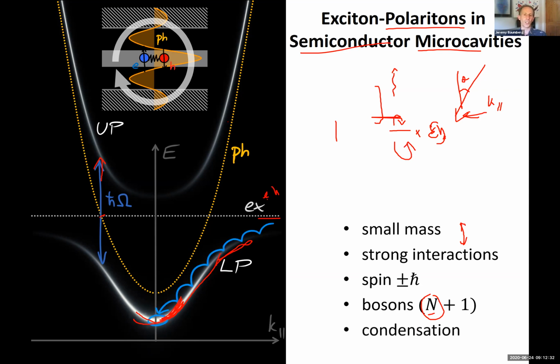So if you excite the system at high energy here, what happens is all the system relaxes down here into this bottom state here, where they live for a time before they escape through the mirrors. And when they're in that state, they can actually phase lock together to form a condensate. And that's what we were really interested in for many years.